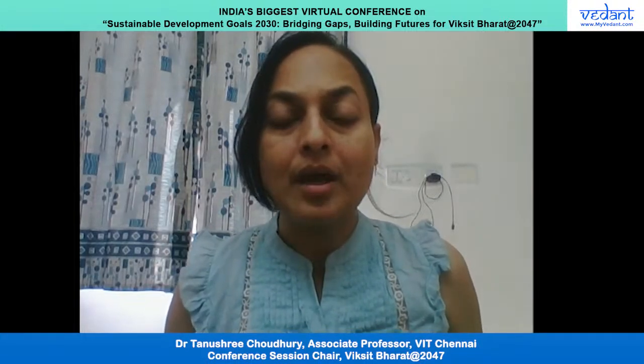And one of my suggestions would be that we can even further reduce this, it can be more than 50%. In order to go beyond 50%, I would suggest the authors try a kind of hybrid composite. Apart from taking the mining rejects, they can at least put some filler materials, the brick clay, the fire clay, which are also rejects.